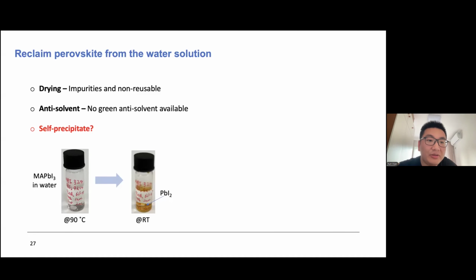And also we were searching for the anti-solvent method. It's also a very typical method that has been used for perovskite crystal growth. But unfortunately, we didn't get any green anti-solvent available at that time. So we were thinking about whether we can make it self-precipitate. That is, we just heat the solution at 90 degrees C or even higher, and then we cool it down to get the crystals, using the solubility difference at different temperatures.